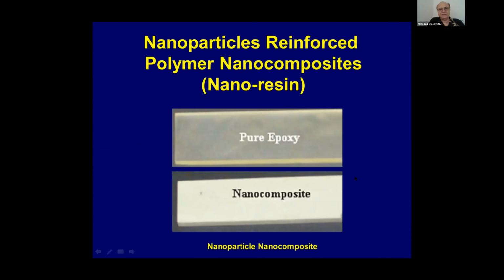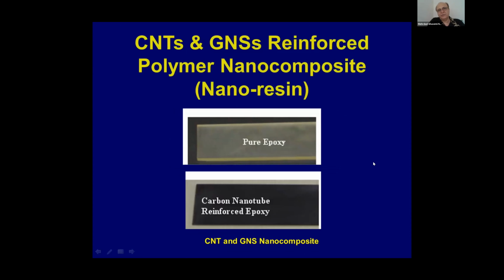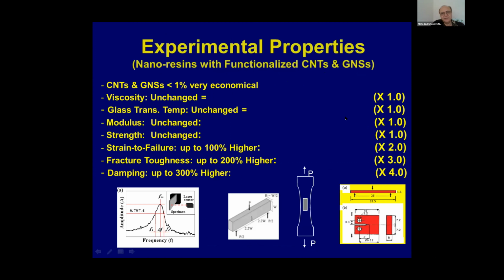So first, Nanoresin. Here we use nanoparticles inside the epoxy system to improve the properties. We also use the CNTs, carbon nanotube, and GNS, that is graphene nanosheets. We functionalize them and put them in the thermoset to improve the properties. So basically, with this inclusion of functionalized carbon nanotube or graphene, and that is less than 1% inclusion, that's the advantage of our technology patent. It's a small amount of nanomaterials you put, albeit functionalized, and you get